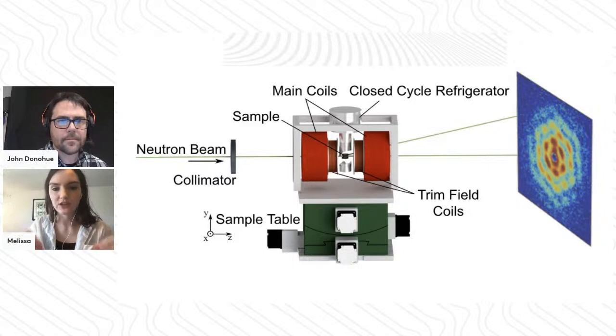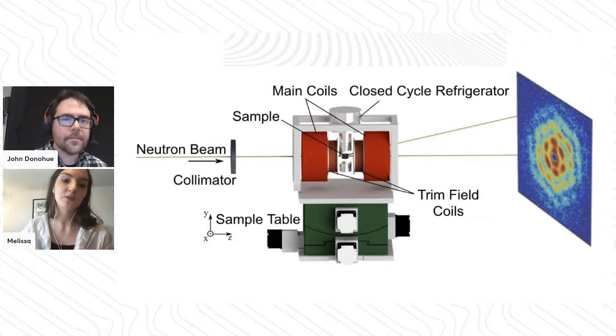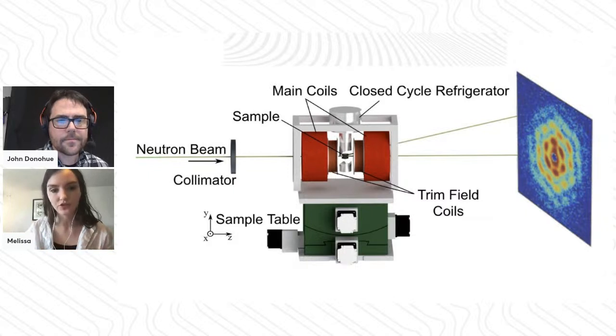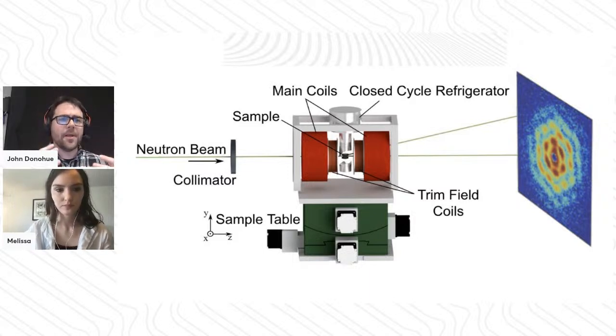That means there's a bit of atomic randomness as to what atoms are distributed on what atomic sites. There's disorder introduced into the lattice as to whether you're going to have a cobalt, a zinc, or a manganese atom. What this does is it introduces slight variations in your exchange parameters. You have a Hamiltonian that governs your system, and that's defined by your exchange interactions, perhaps some anisotropy, your DM interaction, and your Zeeman term. When you're changing the different atoms randomly, you're changing these exchange constants, and that can introduce nucleating and pinning defects.